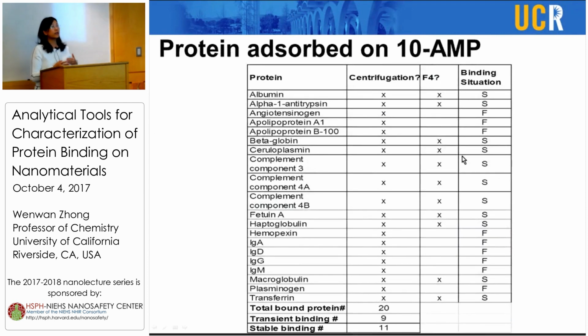So here, if we isolate the particles using our F4, which is a flow field flow fractionation technique, and also for the particles isolated by centrifugation, we identified the proteins on the surface. This is after incubation with depleted serum, meaning we remove the serum albumin and also IgG using a depletion column. But because albumin is so abundant in serum, we still see a lot of it binding. If we identify proteins in both methods, we consider them stable bound protein, and it should be the hard corona portion. For the ones only identified in the centrifugation preparation, we consider them the soft corona portion, with very fast binding kinetics.